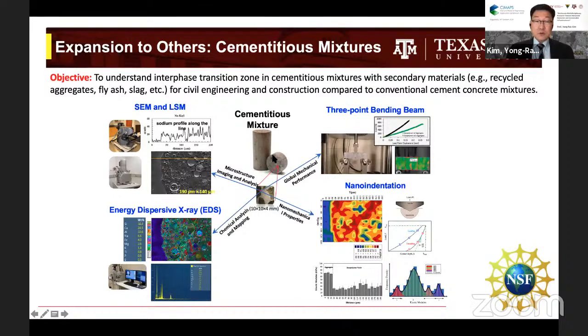So we looked at the interface from four different aspects and combined them all together, like a mapping among them, to better understand what happens. We do small scale microscopic characterization, chemical analysis using energy dispersive X-ray spectroscopy, nanomechanical characterization using nano indentation, and typical laboratory level 3-point bending beam testing.